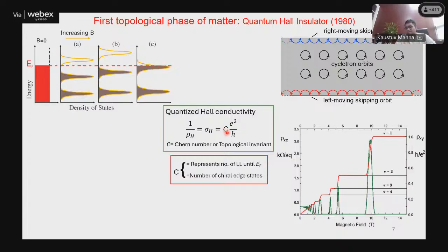What does it actually represent? This represents the number of Landau levels up to that Fermi energy. If the Fermi energy is here, let's say the number of Landau levels is 2, you get 2 times e²/h. You increase the magnetic field. If it goes like this, bottom here, with one Landau level, then C equals 1 e²/h. If you convert this into conductivity, you will observe only 1 times e²/h. 1 means you are in the state of the last Landau level.